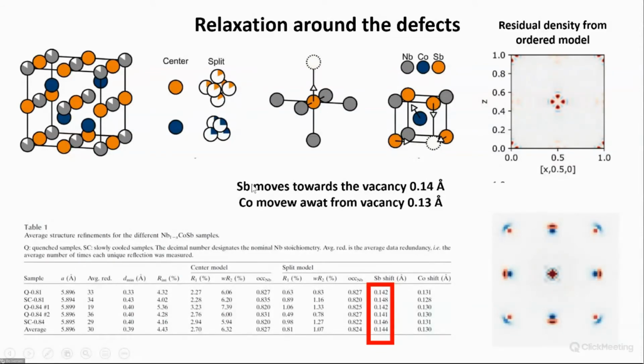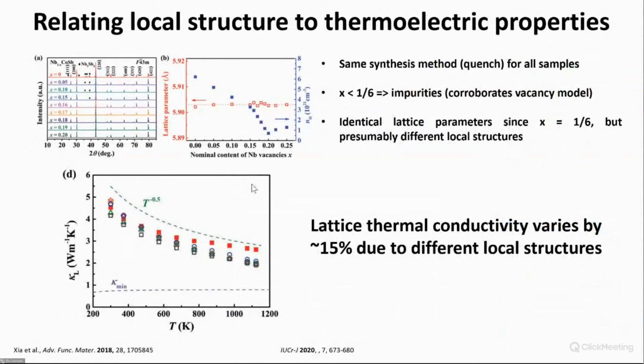So you have this relaxation around the defects, and then you're approaching at least the true chemistry. But then you'll ask, so what's the point? Again, what you really want is to relate the local structure to thermoelectric properties. And then you can look in the literature. Xia et al. made these samples with a lot of different nominal contents of antimony or niobium. And you'll see as soon as you get above 1/6, then you start to have impurities. So the structure wants to always keep 1/6. And indeed, all the samples have the same unit cell.